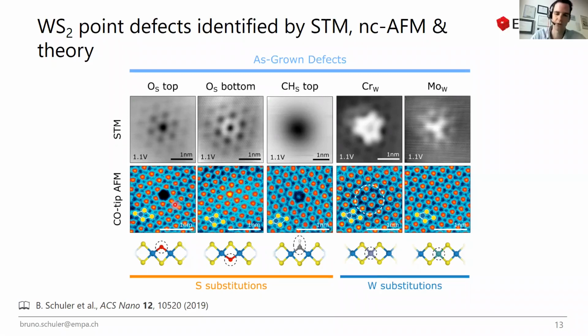And what we observed is that there are a lot of substitutional defects. For instance, oxygen substituting for sulfur is a very abundant one, and we see those very consistently throughout all the samples, grown in different ways. And it's just a defect which has a very low formation energy. And oxygen, of course, is also a chalcogen itself, so just from chemical intuition, it makes sense that this is also a very low energy defect to form.